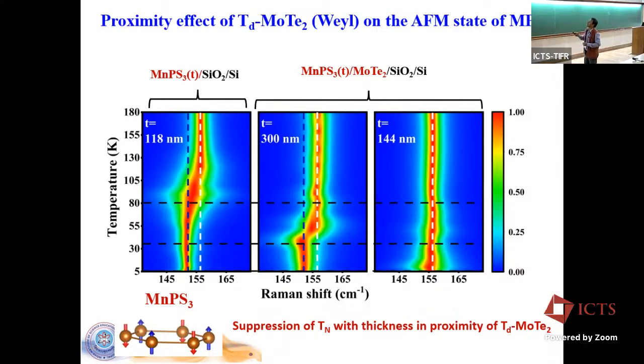Now, what he did, he created a heterostructure of MnPS3 on top of MoTe2, and he tried to understand what is happening in the magnetic response. Now you see, this is without the MoTe2 in between. This is just the MnPS3, about 100-something nanometer thick. As usual, it's robust. It shows the transition around 80K. But now a thicker sample put on MoTe2, you see the transition is happening somewhere around 30-40 Kelvin, 35 Kelvin. So the 80 Kelvin Néel temperature has gone down to about 30-35 Kelvin, even for thick samples.